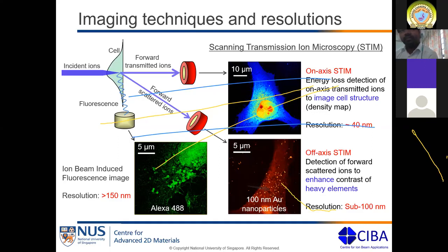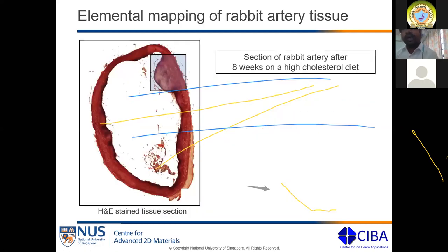Then you have direct transmitted ions, and you detect them using a particular detector, which is called on-axis STIM, and then you have off-axis STIM. So the difference from this image, you can see that between on-axis and off-axis STIM, you can actually increase the contrast using off-axis STIM. So you can see the small particles which are not much resolved in case of on-axis STIM. So this is the beauty of doing off-axis, right? Okay, the next slide, I'll show rabbit artery tissue.